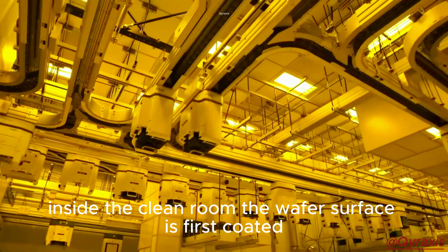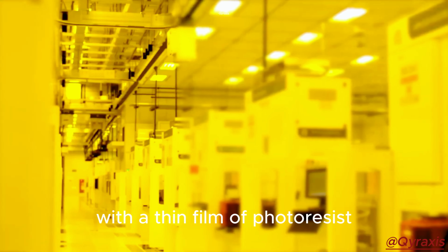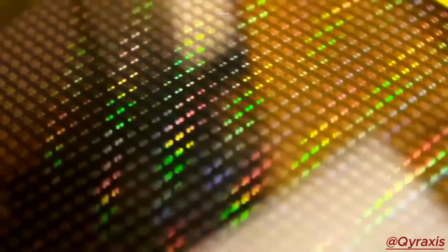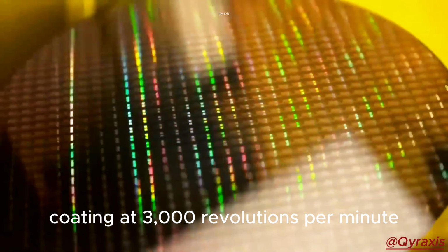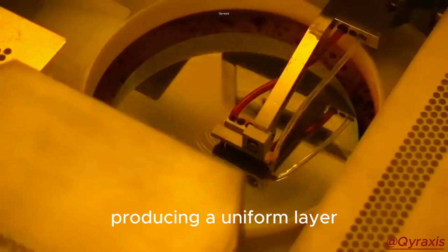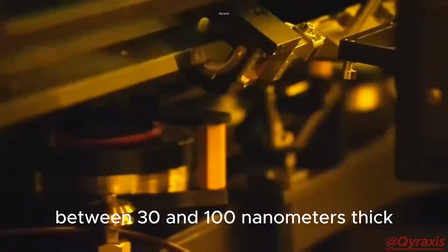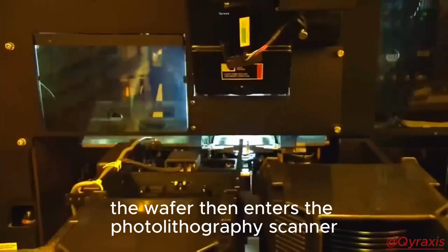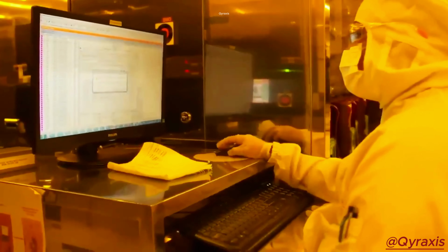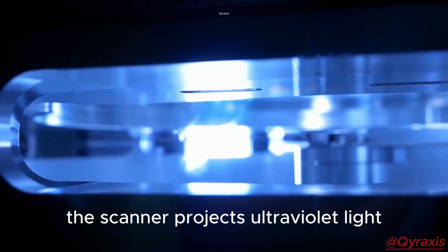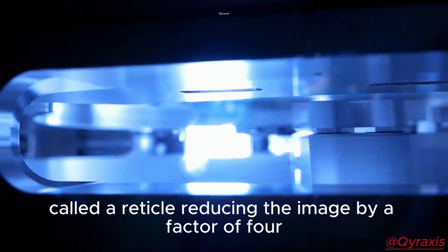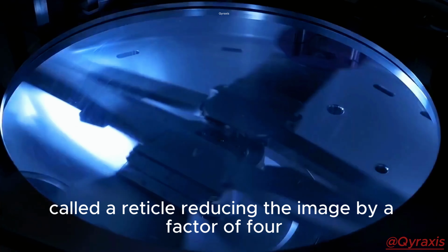Inside the clean room, the wafer surface is first coated with a thin film of photoresist, a light-sensitive polymer, applied by spin coating at 3,000 revolutions per minute, producing a uniform layer between 30 and 100 nanometers thick. The wafer then enters the photolithography scanner. The scanner projects ultraviolet light through a patterned quartz mask called a reticle, reducing the image by a factor of 4 and focusing it onto the wafer surface.